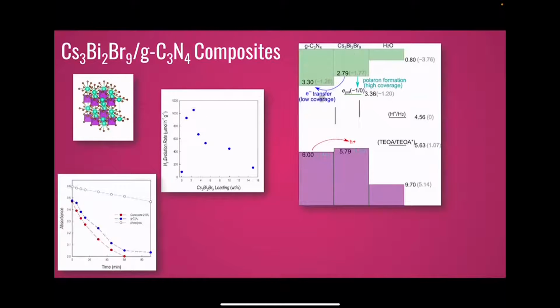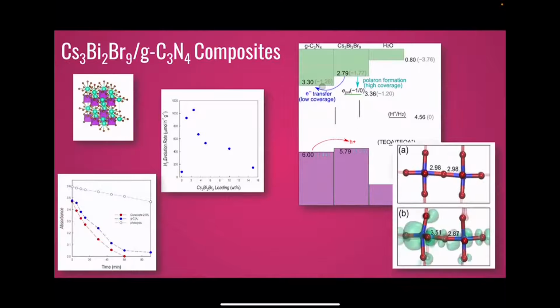Also in this case, we have a good electron transfer between the perovskites and the graphite carbonitride. And thanks to our colleague in Perugia, we could also interpret the behavior of the hydrogen evolution reaction as a function of the loading of the perovskites, which has a maximum and then decreases. I will not go too much into the details.